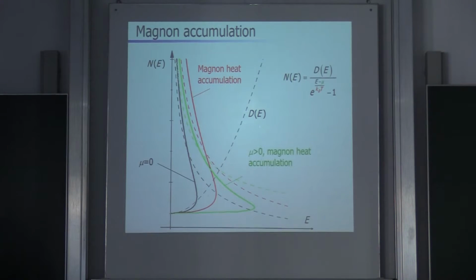So the only way to realize something like that is to change the form of the distribution function. And one way to do that is to introduce the magnon chemical potential. So assume that this is not 0 anymore, but it becomes a little bit larger than 0. Now, if we take mu larger than 0 and allow T to become the phonon temperature, so that the magnons lose their energy to the phonons, but change the distribution function according to a certain mu, you get a distribution function like this green one here.